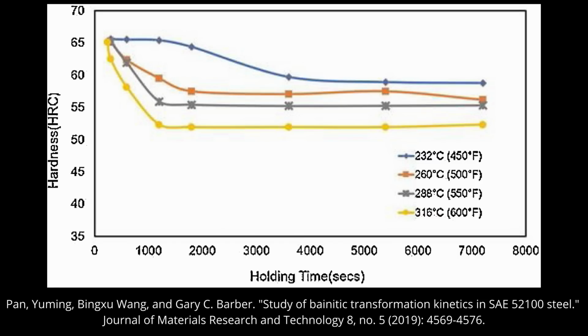Another thing you can do is just make sure you're holding for long enough. All of the experiments I did for this video, I held for at least 2 hours. You know, that period of time is not a big deal for me. If you're trying to save yourself time, you can find the point at which it's fully transformed and not have to have longer austempering times. But to sum it all up, you can find how long it takes to transform by measuring the hardness after different austempering times.